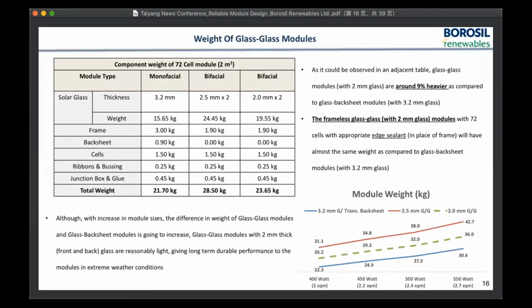Yeah. So the weight of the solar module was something that we were discussing. If you see this 3.2 mm front glass of a monofacial module, all things put together, the weight of the module is around 21 or nearly 22 kg. Now, if I use a bifacial module with 2.5 mm glass on both sides, the weight increases to around 28 and a half kg, which might be an issue. So there is a solution. Instead of 2.5 mm glass, if we use fully tempered 2 mm glass on the front and maybe heat strengthened glass of 2 mm thickness at the back, the module weight is now 23.6 kg, which is almost 9% higher as compared to the normal monofacial module.